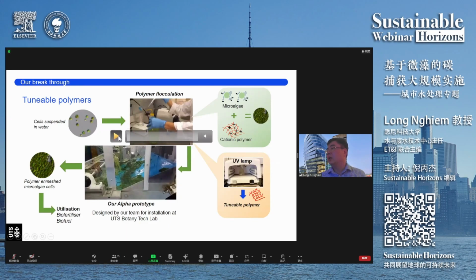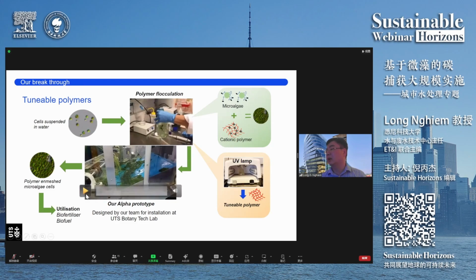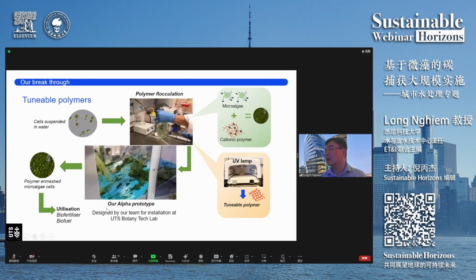So armed with that knowledge, we have now successfully developed a polymer, and our polymer is actually very effective. By adding a tiny bit of our polymer, you can see in this video that a tiny bit of polymer can allow the microalgae solution to aggregate in no time. And once it aggregates, we can then separate and recover the microalgae aggregate using any sedimentation or flotation device. So in this case, we have set up a pilot system where we add polymer into the microalgae solution.